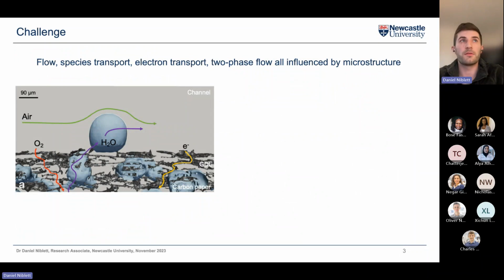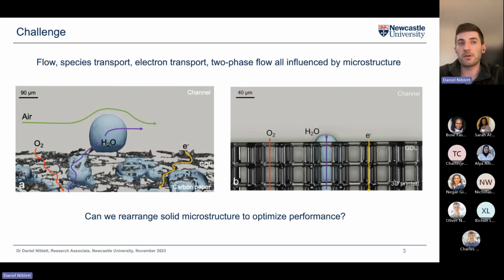So the challenge with electrodes in electrochemical devices is that the materials interact with flow, species transport, electron transport, two-phase flow, and these are all affected by the solid microstructure, as you can see by this image here. It can be a complex stochastic arrangement of solid particles. So the idea is, can we rearrange the solid microstructure to optimize the performance of these transport processes, which means you essentially get the oxygen to your catalyst at a higher concentration, or you remove your products easier from your reaction sites. And this isn't specific to fuel cells, it could be related to electrolyzers, batteries, or anything like that.